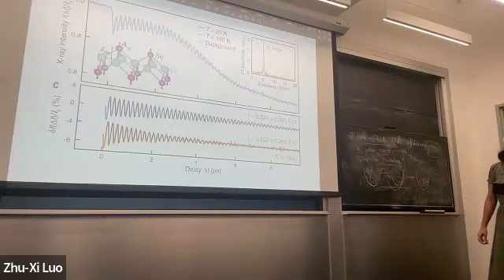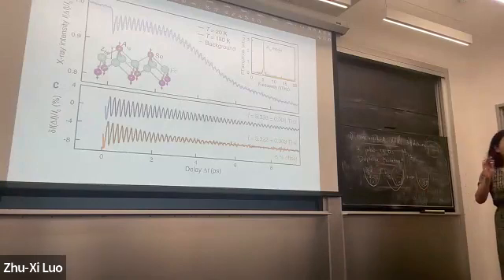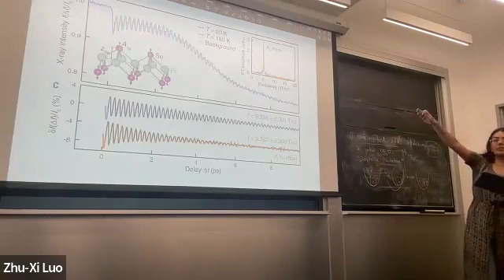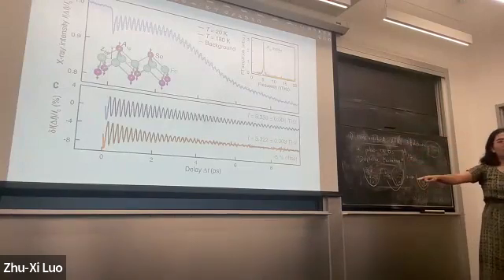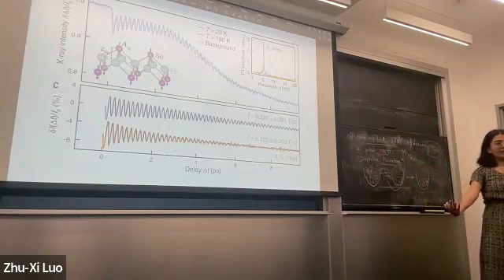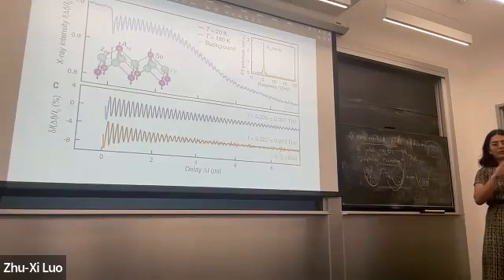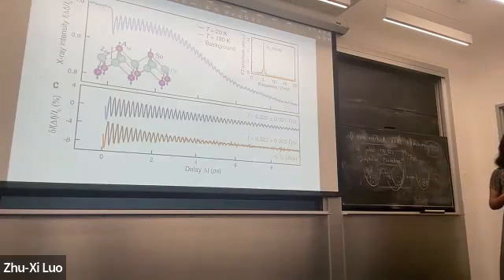Oh yeah, that's a good question. So I think in general, for a non-time resolved, an equilibrium X-ray diffraction experiment, you also see a similar decay. You see this overall decay amplitude, just called the Debye-Waller effect. And from my understanding, it's just down to other thermal processes that are happening in your sample that eventually sort of kill your signal. So it will eventually actually go back if you wait longer.